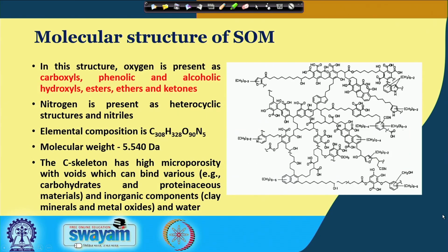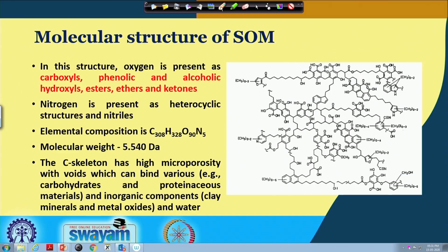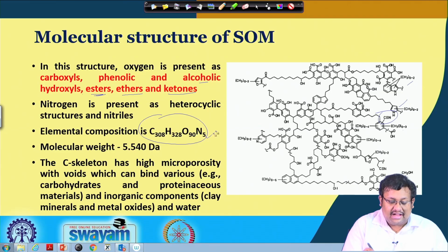And in this structure one thing is clear, that oxygen is present as carboxyl. As you can see, the oxygen here is present as carboxyl, and then phenolic groups are also present, and then alcoholic hydroxyls are there, then esters are there, ethers are there and ketones. So, all these different groups are present, and nitrogen is present as heterocyclic structures and nitrile. As you can see, these are different heterocyclic structures, and the nitriles you can see here. And the elemental composition is basically C308 H328 O90 N5, and molecular weight basically they have calculated is 5,540 Dalton.